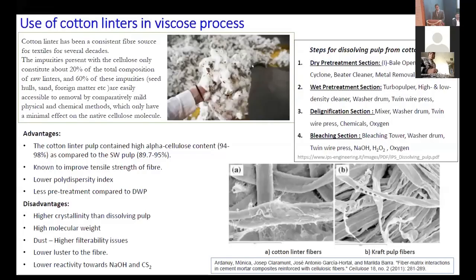And it needs less pre-treatment compared to dissolving grade pulp, because in dissolving grade we have a very high concentration of hemicellulose and lignin. In cotton we do not have that much. But a disadvantage is higher crystallinity. Generally, our dissolving grade pulp has lower crystallinity because of the pulping process, the harsh treatment of sulfite and caustic. Then it has very high molecular weight, very high dust count, low luster, and low reactivity towards NaOH and CS2. So which basically limits the use of cotton in the viscose process.